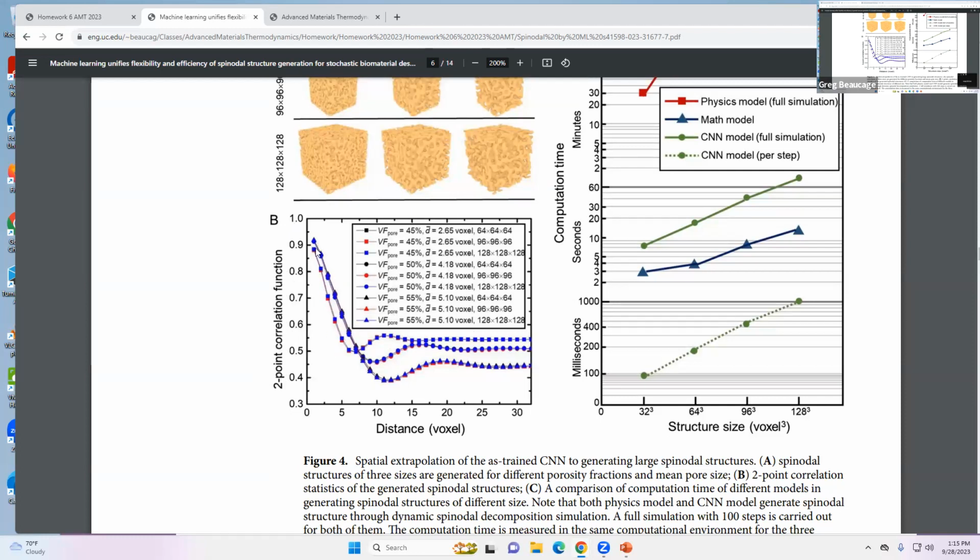So that's good. There's another little twist about correlation functions. There's a linear part at the beginning where it's like a number plus the surface to volume ratio times the size. So the slope here is the surface to volume ratio, which means the steeper slope has smaller sizes, because smaller things have a higher surface to volume ratio. So the steep one is small and the other ones are larger, right? And these are at different volume fractions, and the squares are 45%. So it's good. The low volume fraction has small sizes. That kind of makes sense.